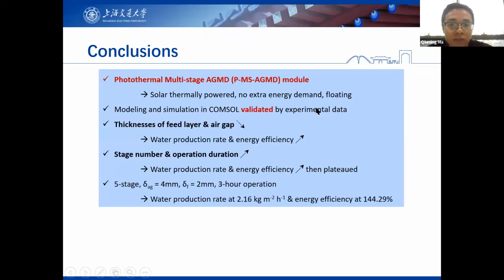So lastly, the conclusions. Here in our lab, we designed a photothermal multi-stage AGMD module, which is totally 100% solar energy powered without extra energy demand, and it can be floated on the water surface for a passive operation. And we built the model in COMSOL, and it's validated by our experiments. And when we play with the parameters, we can see with the thinner feed layer and air gap, both the water productivity and energy efficiency could be increased. And when it comes to higher stage number and operation duration, also the water production rate and energy efficiency increased, but they first increased, then plateaued.